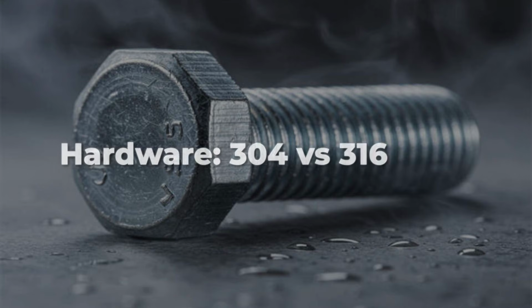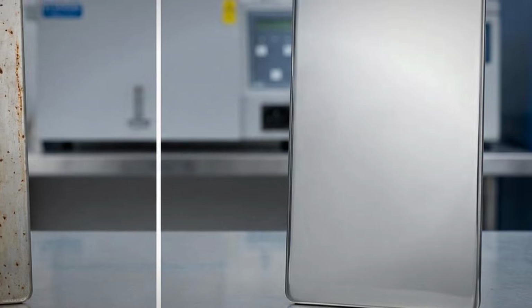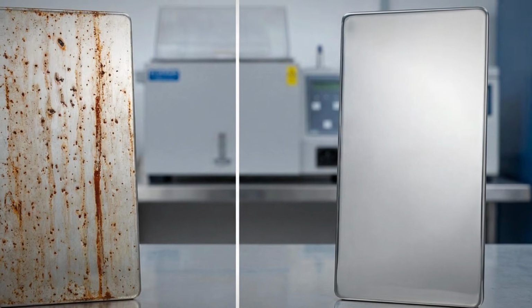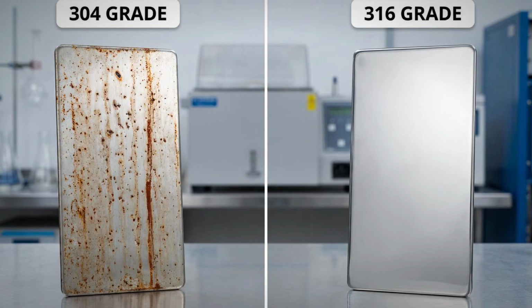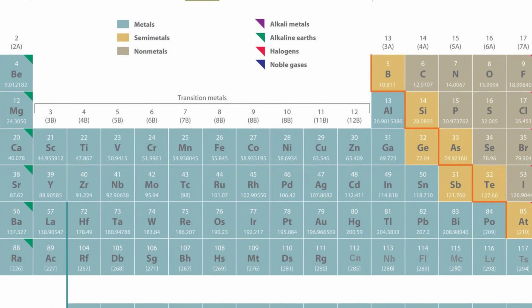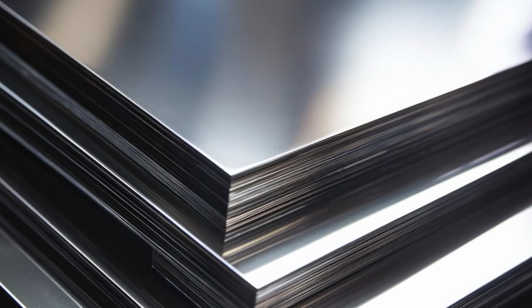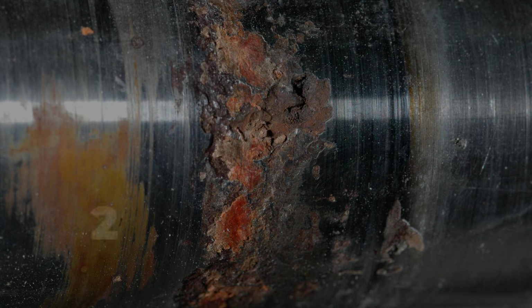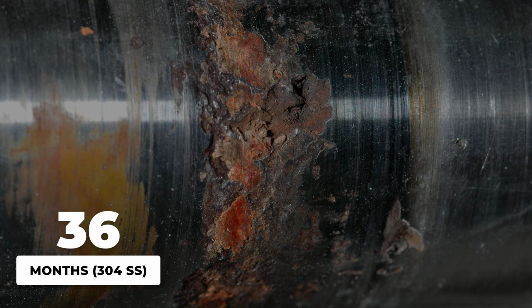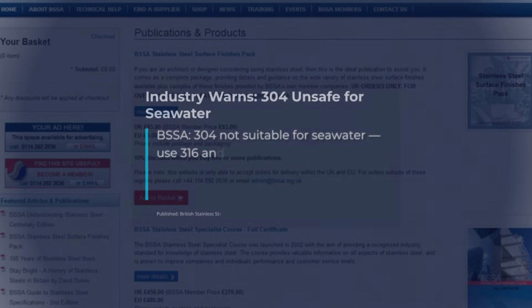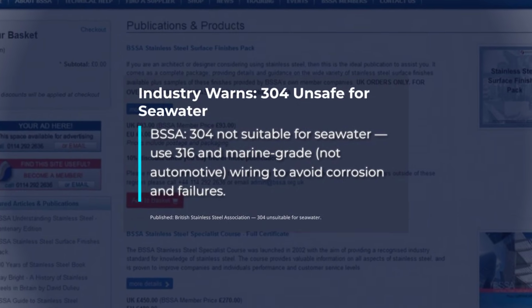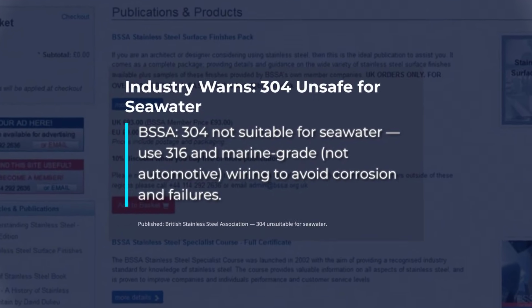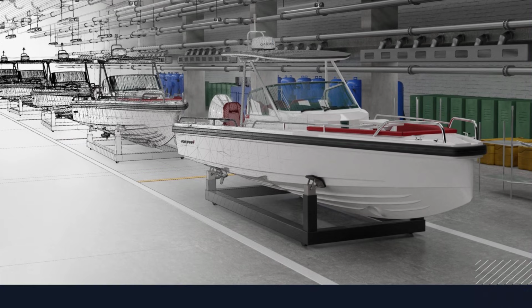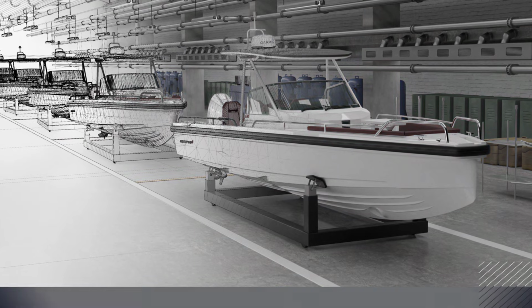Now let's talk about the hardware bolted onto your hull. The difference between 304 stainless steel and 316 stainless steel is 2 to 3% molybdenum. You cannot see the difference. They look identical. But 304 develops rust pitting within 36 months of saltwater exposure. The British Stainless Steel Association says flatly that 304 should not be considered suitable for seawater. Guess which grade is cheaper and shows up on budget boats.